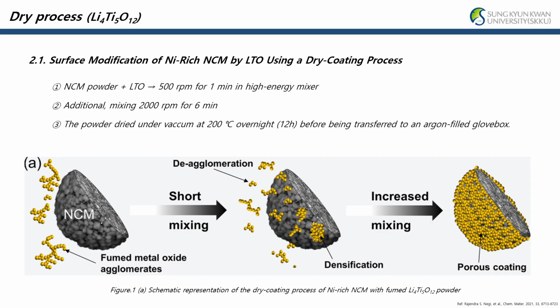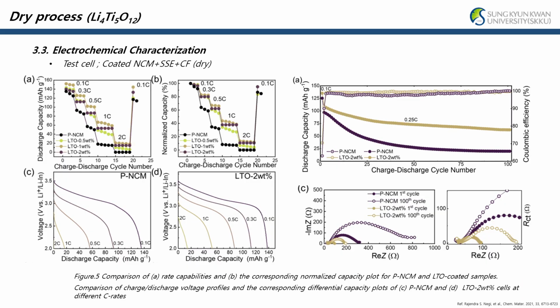Put the cathode active material and the material to be coated in a dry coating machine. Mix the coating material particles at a low RPM for about 1 minute and then mix the coating material at a high RPM for about 6 minutes to adhere better, and dry it in a vacuum oven to remove moisture. Comparing the electrochemical